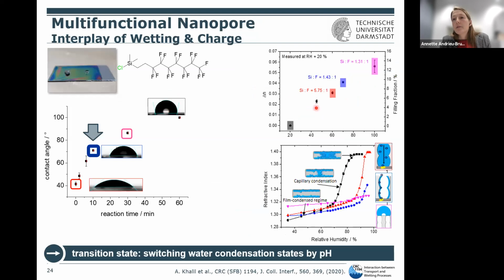Oops, and this is the data that supported our hypothesis here. What we did is water adsorption measurements, so changing relative humidity and measuring the refractive index with the ellipsometer. And what you see here in this blue curve is that at very high relative pressures, you still get water into the pores, whereas in the high contact angle, no water condenses anymore.